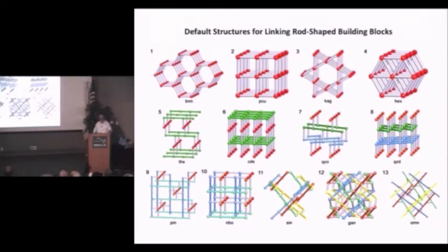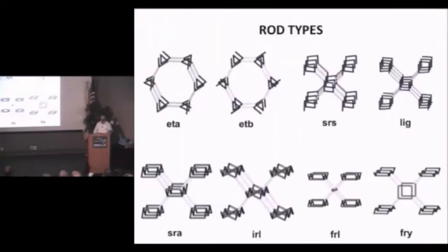but always linked by these gray units, which would be the organic units. So all these allow us to overcome a difficulty with MOF structures, which has been the interpenetration, where as you open the pore, oftentimes you have frameworks that catenate or interlock mechanically so as to reduce porosity and make more stable structures.